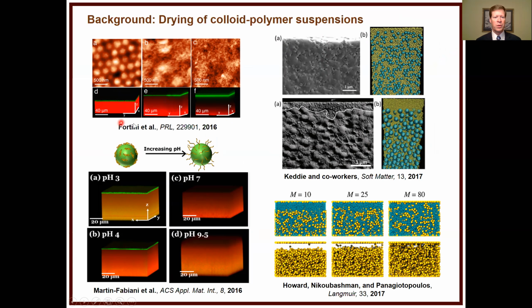And so whether you're just using confocal microscopy to get average density and scan, and then of course here where they're showing AFM of the top surface, or even looking at changing particle size to dynamically change the particle size ratio to look at partitioning or segregation in these systems. Now, most studies that are experimental actually do what's up on the right-hand side, which we've seen already many examples of, where you section, you use like cryo SEM or SEM to section your film, and then look where the particles inside went. But of course, the challenge there is you can't see while it's happening.